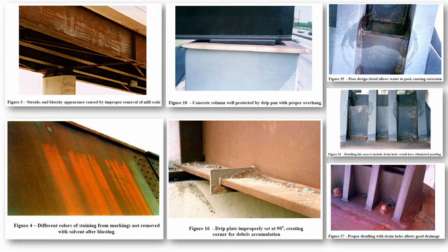Fundamentally, in terms of performance, we saw no durability problems with any of the Texas bridges. We looked at 30. There were 2 over salt water. The two that were over salt, really brackish water, had formed the patina. The other bridges we looked at had not formed a patina yet. It was actually a very slow process. This includes Houston, which gets a lot of rain. Of course, we do have good wet-dry cycles.